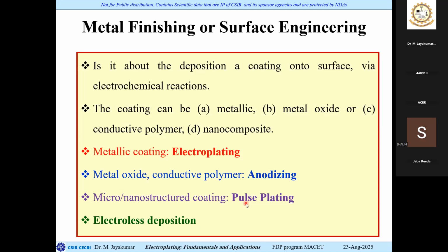So compared to continuously giving some current, say 1 ampere, for a very long time, you have a pulse technique, on, off, and there is an additional technique called the reversible pulse technique, where you switch on for some time, metal gets plated, and then you dissolve part of the surface. So there is better sticking. Sticking, in electrometallurgy and electroplating, is called adhesion. Sticking is done very easily. So pulse plating is an advanced technique used in developing special coatings. There is also something called electroless deposition. When they say electrolysis, electrons are involved.